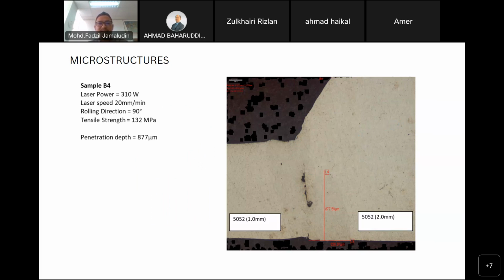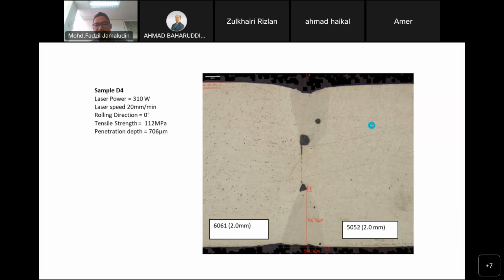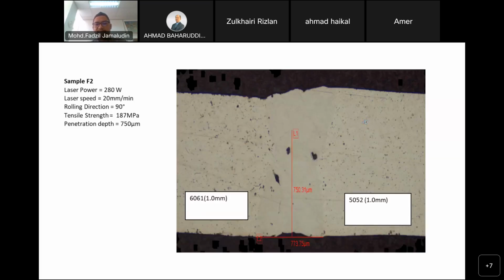Okay, for the same alloy but different thicknesses, this is much more clear for the same thickness of 2 mm. You can see that for 2 mm it cannot be done because the penetration depth is only 700. So you have some areas which are not being welded. This is one of the reasons why the samples have less tensile strength, because only a portion of the sample is being welded. And this is a good example showing that the welds are overlapping on both sides. So for 1 mm and 1 mm